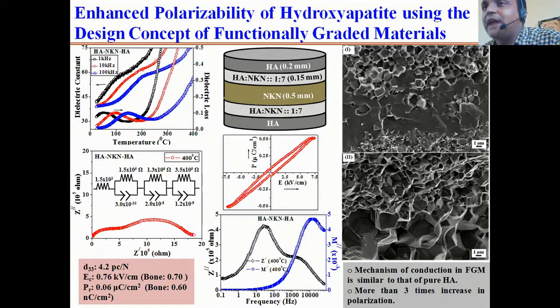So here, what has been done? This NKN, if you see in the middle of the slide, the NKN is written. This NKN refers to sodium potassium niobate. This sodium potassium niobate is actually the best known piezoelectric biocompatible material so far. Okay, this is the best known piezoelectric biocompatible material so far. So a layer of sodium potassium niobate has been introduced between the hydroxyapatite layers.